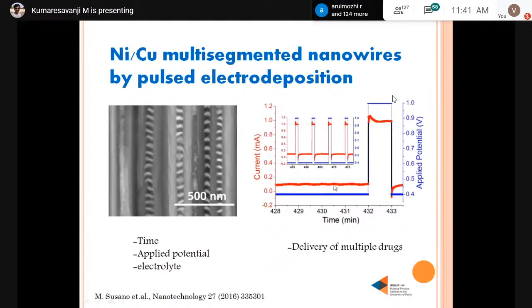So if we apply pulse electrodeposition, we can prepare such multi-segmented nanowires or nanotubes also. It is achieved just by optimizing the time, the applied potential, and the electrolyte. And these multi-segmented nanowires are used for delivery of multiple drugs.